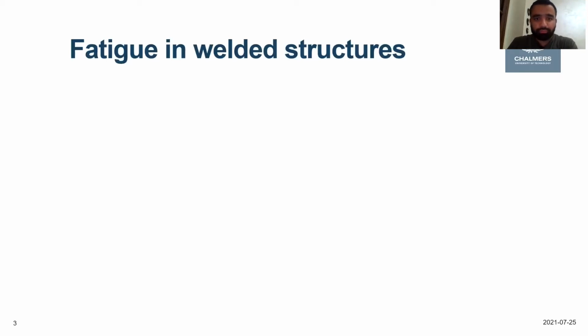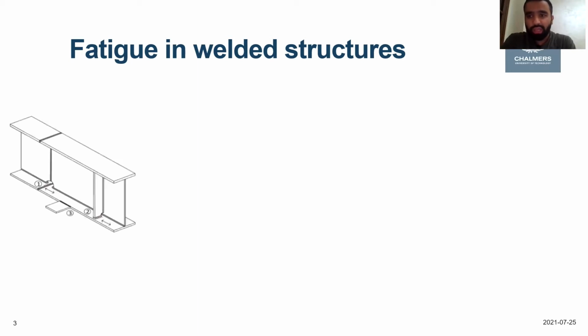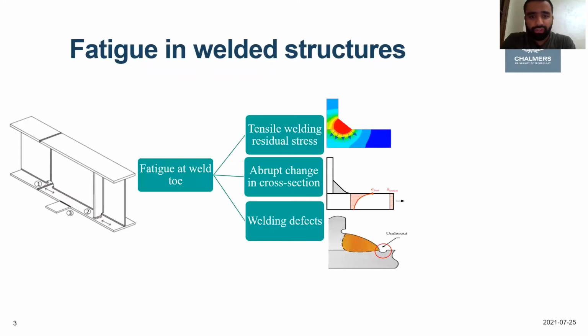To start with, why do we care about fatigue in welded structures? Whether it's for bridges, whether it's railway or road bridges, once we are doing welding, we have different positions to weld, whether it's transverse attachment, butt weld, cover plates, rat hole, and so on. We always create three different negative effects. So first, we put a lot of thermal expansion and contraction in a specific location, which causes tensile welding residual stress to take place at the weld toe.